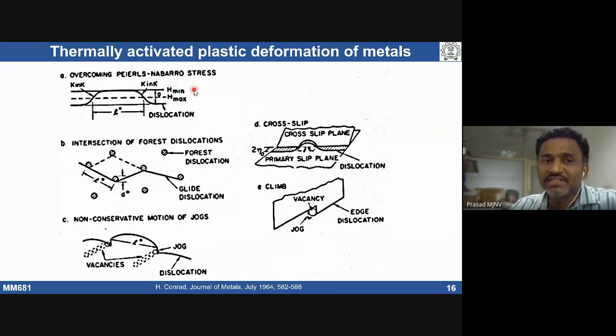So these are the thermal barriers you are seeing: overcoming Peierls-Nabarro stress, intersection of forest dislocations. Forest dislocations thread the gliding planes, which involves all kinds of barriers, Lomer-Cottrell locks, all of which can control the gliding activity, and non-conservative motion of jogs, which are of small atomic sizes, cross slip activity and climb activity. All these things come under the category of thermal barriers. That means they can be thermally activated; by giving a temperature I can easily activate these barriers. So these are called thermal barriers.